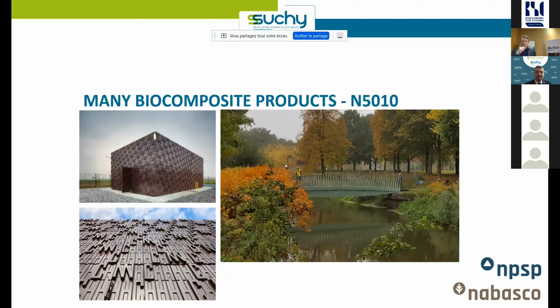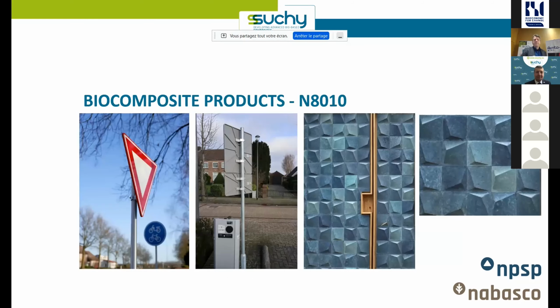Well, as I said, we've been producing biocomposites since 1998. We've been building facades. We did a test with a bridge where we could go to a bio-based content of 98% in volume and 89% in weight. We work with hot pressing techniques, so this is a BMC technique. We bring this to the market at this moment for traffic signs and facade panels. And here we use a lot of waste streams. So we use a filler.